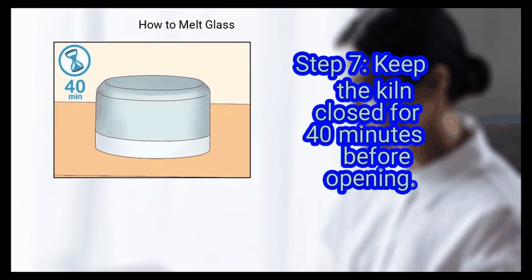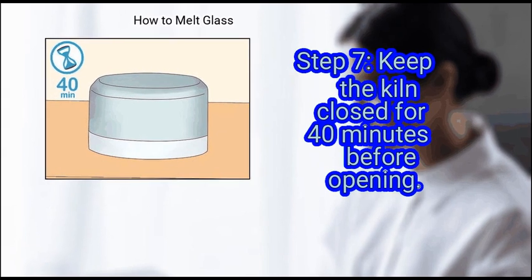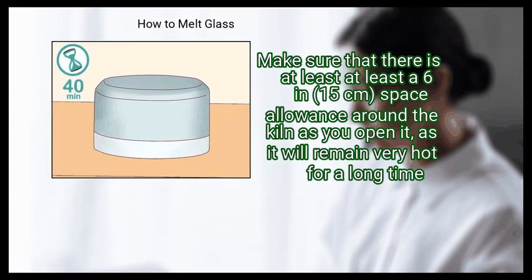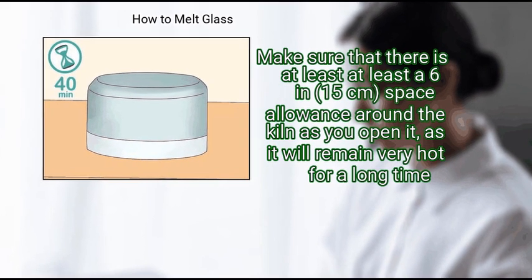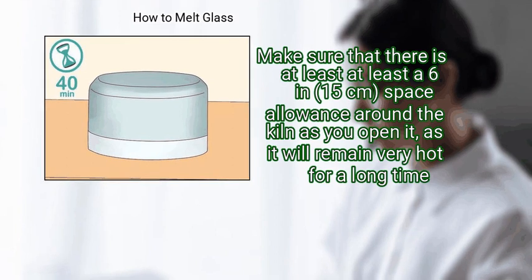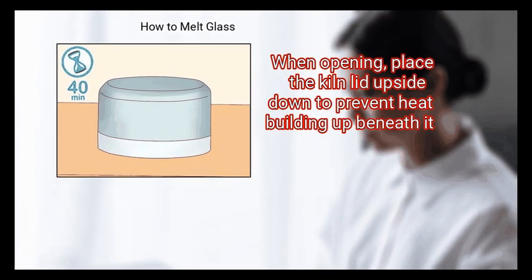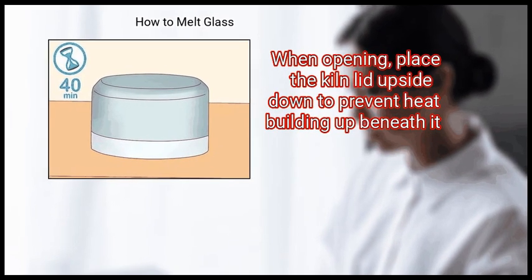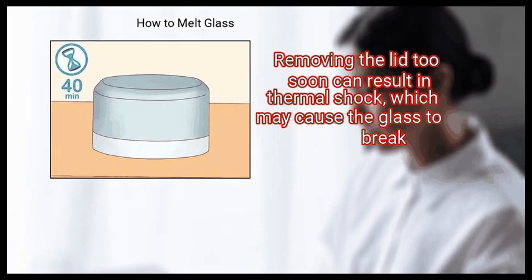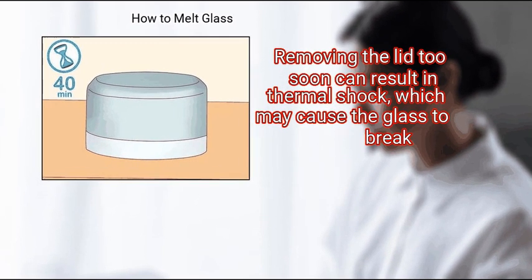Step 7. Keep the kiln closed for 40 minutes before opening. Make sure that there is at least a 6 in (15 centimeters) space allowance around the kiln as you open it, as it will remain very hot for a long time. When opening, place the kiln lid upside down to prevent heat building up beneath it. Removing the lid too soon can result in thermal shock, which may cause the glass to break.